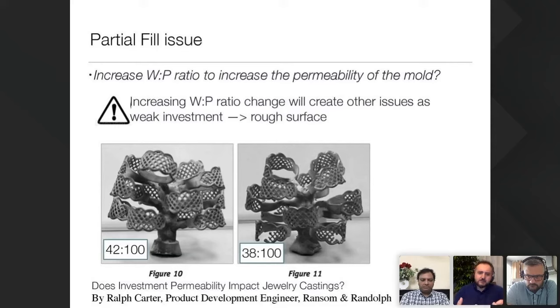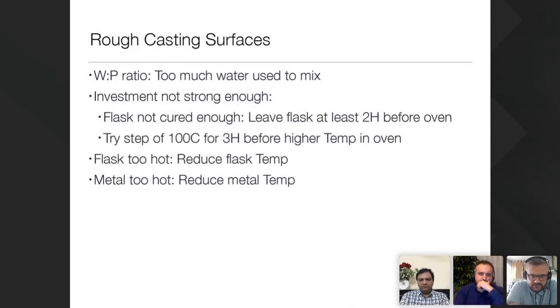But if you do that, it may help, but be careful, because when you increase the water, and we will see in the next slides, you will have issues with the surface. So playing with the water powder ratio is risky, right? Any comments on that? Very risky. As you've said here, weak investment, you'll end up with flashing, rough surface. The correct investment powder gives you the correct permeability to start with.